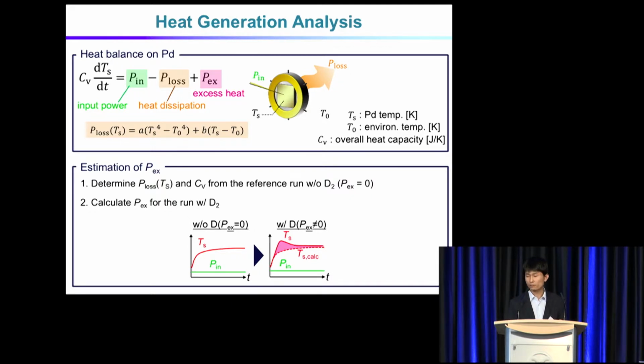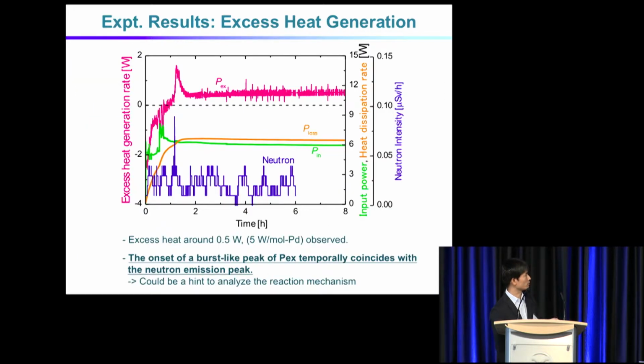And then we estimated the excess heat generation by calibrating the heat capacity and heat transport parameters as shown here. We first ran a blank control experiment without deuterium loading, and then defined the parameters for heat conduction, accounting for the radiation as well as convection diffusion transport of heat. And then the fitting result was almost perfect, so we are relatively confident of the calibrated parameters. And the result is like this red curve. This is excess heat. This is the 0 point, so break even.